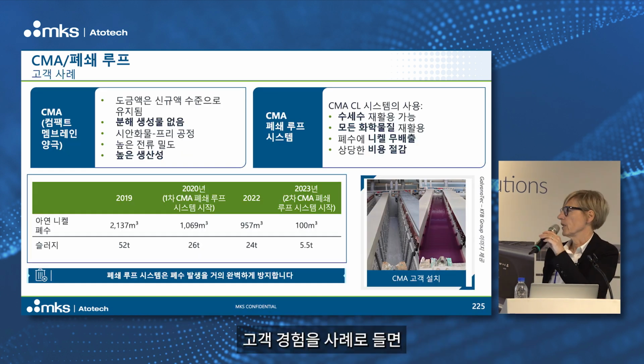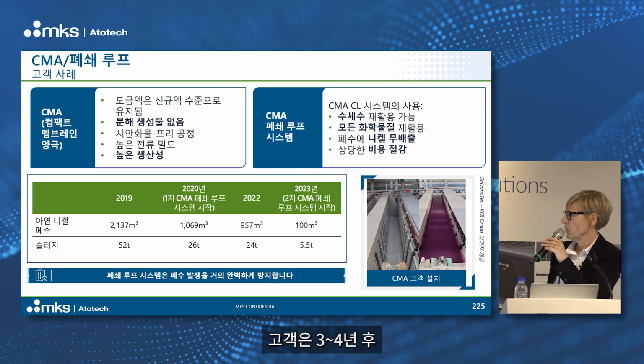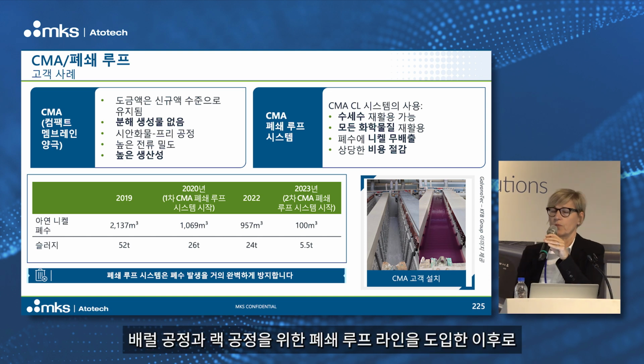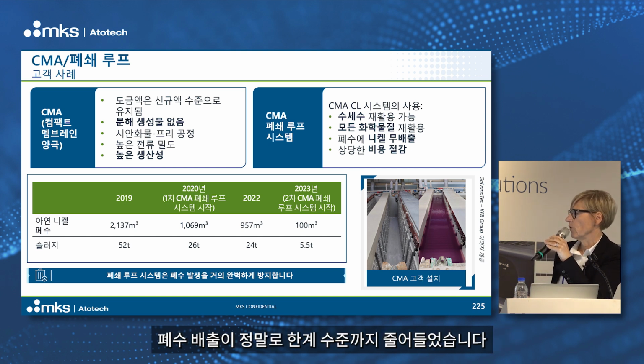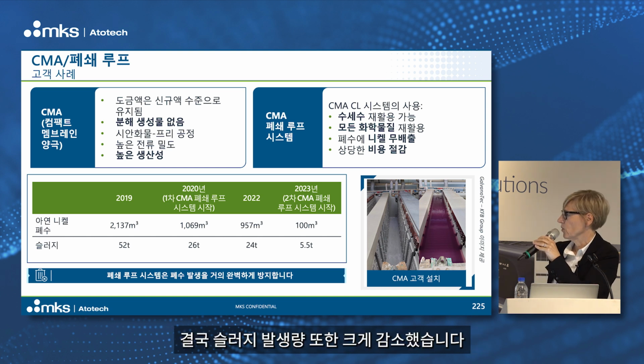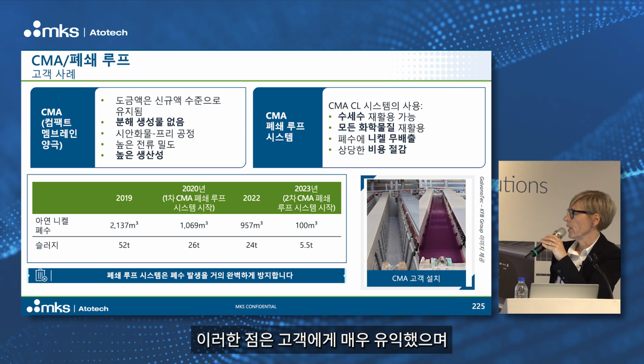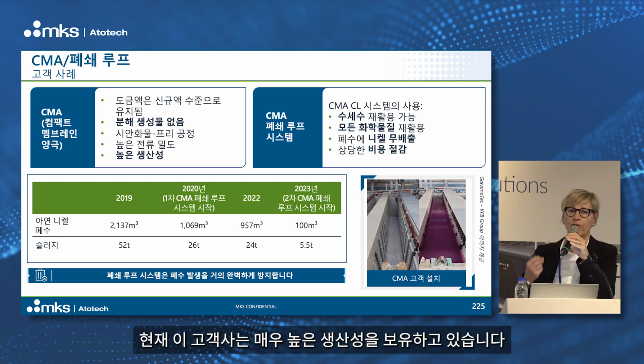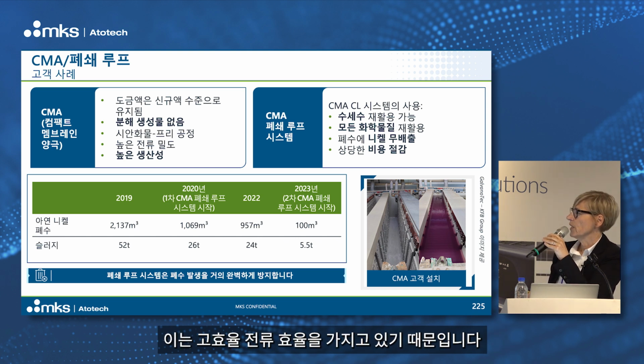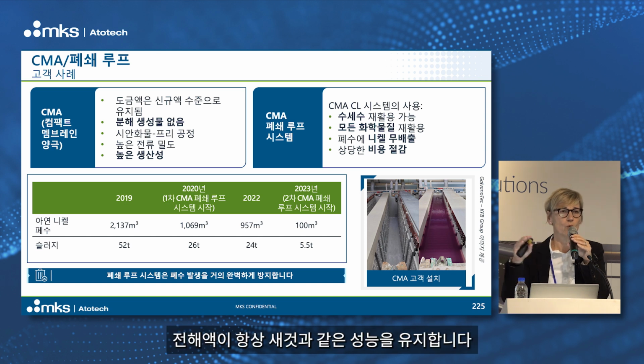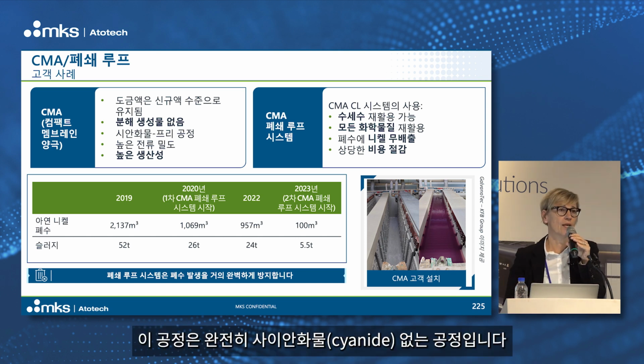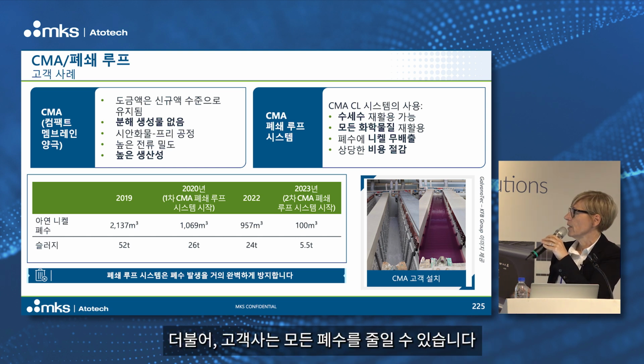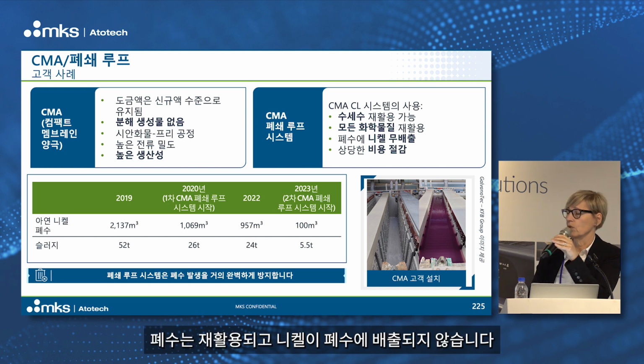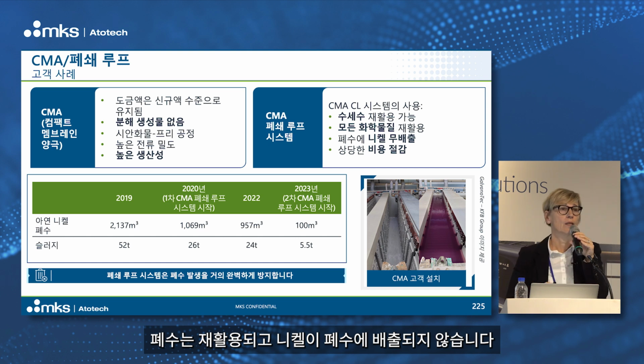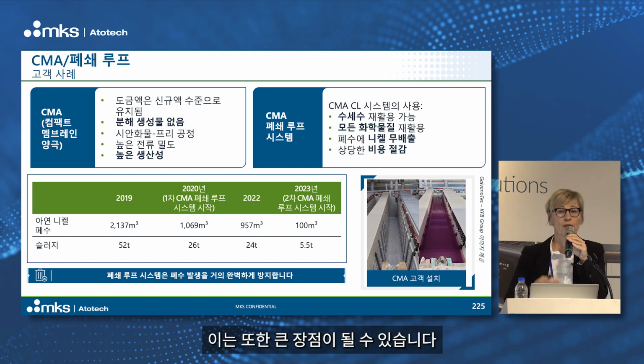If you see this example from a customer experience, after 3 or 4 years, when this customer had two closed loop lines implemented, one for barrel and one for rack, his wastewater was really going down to the limits, and at the end also his sludge was going down dramatically, so very helpful for him. His advantage is that he now has a very high productivity because we have a high current efficiency. He has no breakdown products in his electrolyte. This electrolyte stays always at new performance, like a new electrolyte. It is a totally cyanide-free process, no cyanide in. And at the end, all his wastewater is recycled, and he can have no nickel discharge to the wastewater. That can also be a big advantage.